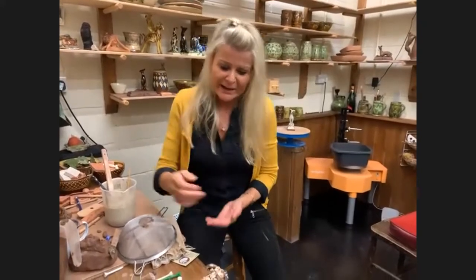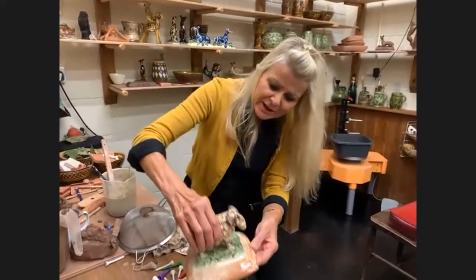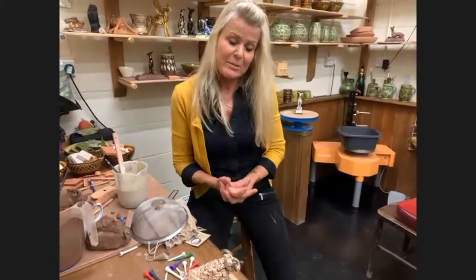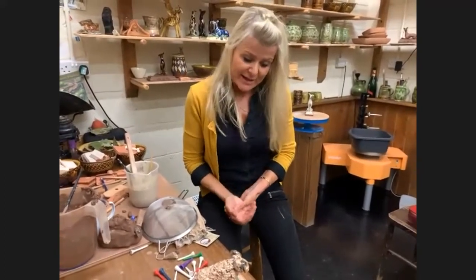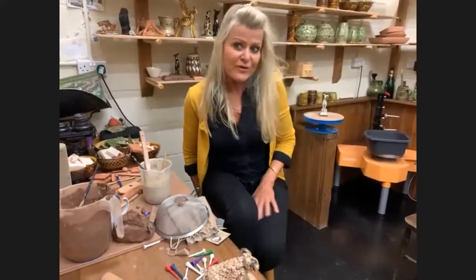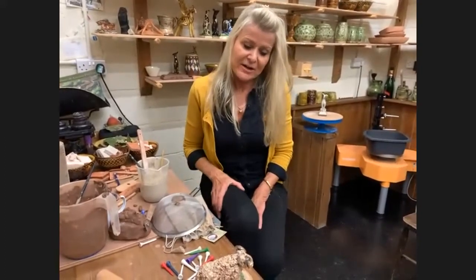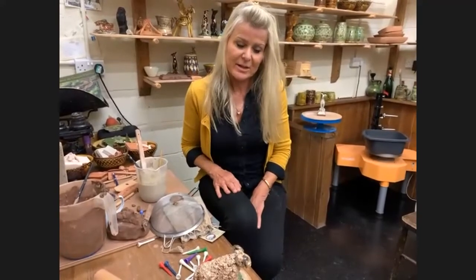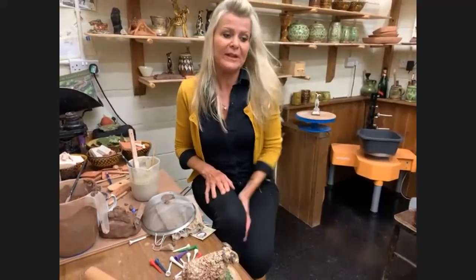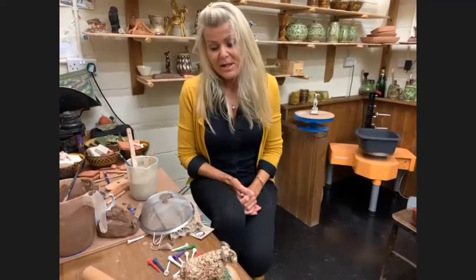Yeah. It's basically the recipe that Jeff uses. And I've stuck with that. I did way back, and actually it was probably around this time, it wasn't melting, it was staying quite buttery and opaque, and it was a bad batch of flint. That's what we put it down to. So I used Josie Walter's no flint glaze. Josie's very, very generous with her recipes and things. And I used that for a while and it worked, but I bought a new batch of flint and away we go. So it works well.